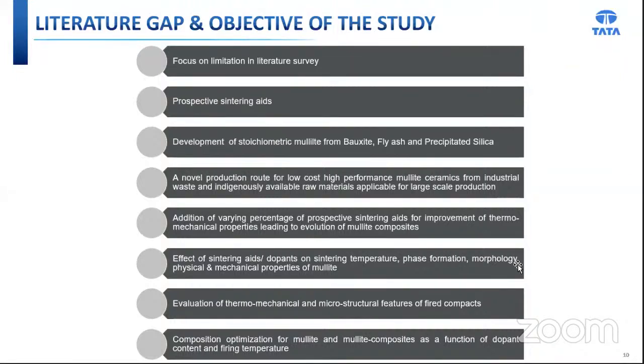Why has this study been undertaken? There are a few objectives. The first one: investigations regarding synthesis of mullite ceramics have been carried out exclusively either from fly ash or from bauxite, but no such in-depth research in the alumina region of the silica-alumina binary system using fly ash and bauxite in the presence of prospective sintering aids such as sintering boehmite has been carried out. Number two, the processing temperature is very high in the reaction sintering process. So with an aim to reduce the temperature, we have to add some prospective sintering aids with an optimum content.